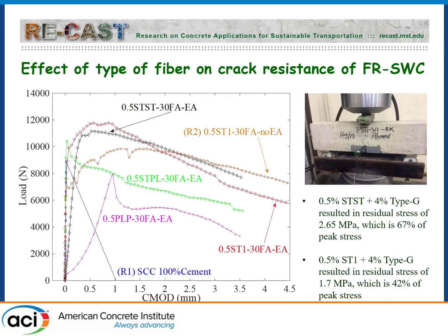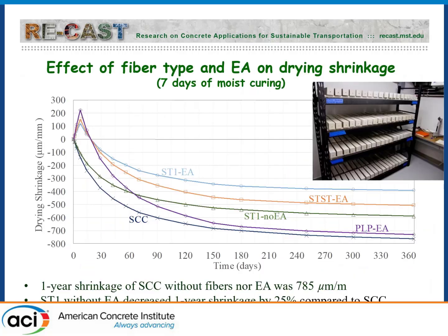We also did the crack mouth opening displacement test versus a single point loading in the middle with a notched end. And as you can see, the steel fibers again gave you a lot of residual strength, a lot of ductility, a lot of fracture toughness. So the decision was to use the combination of micro-macro steel for rehabilitation of this bridge.